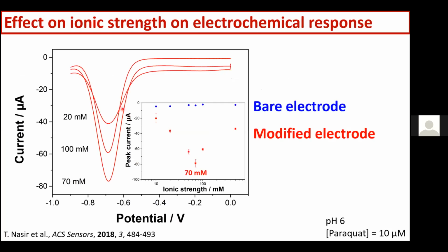Okay, one of the other things that we have been looking at is the effect of the ionic strength on the electrochemical response of paraquat. So here is the square wave voltammetry of paraquat for 3 different ionic strengths: 20 millimolar, 100 millimolar, and 70 millimolar. And we found that the best ionic strength was 70 millimolar, and here you have the peak current as a function of ionic strength, and you can see that we have the maximum reductive current for 70 millimolar.